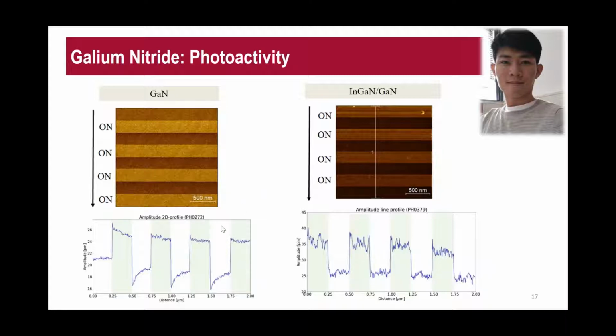That's the piezoelectric coefficient. So we are using a light source to excite GaN, and we can see the response from here. If it is off, the amplitude will be somewhere around 20 to 22 picometers, but if it is exposed to light, it will have a jump. All right, so this is how we study the strain behavior of GaN. If you look at the interface between GaN and InGaN, it is actually able to double the strain behavior in response to light. So this will lead us to further understand the strain activity in GaN materials when exposed to light, and ultimately how it will affect LED applications as well as solar cells.